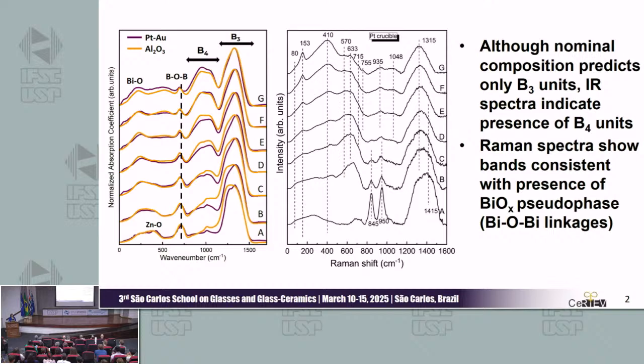And the presence of zinc and bismuth in this system is not a simple mixed modifier effect, but zinc and bismuth are affecting the borate speciation in very different ways. In the case of zinc, it is causing a disproportionation, and in the case of bismuth, there can be agglomeration of bismuth within the network, forming these bismuth-oxygen-bismuth bonds, or linkages.